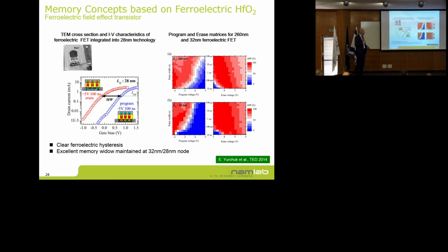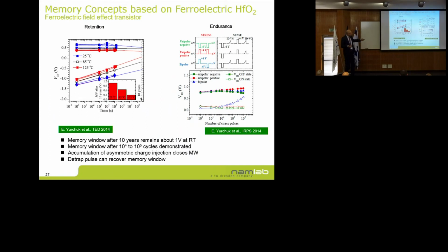And this slide shows that it really scales very nicely. So it compares ferroelectric field effect transistors that we fabricated together with Global Foundries with 260 nanometer channel length and 32 nanometer channel length. And you see that the programming curves are more or less identical. And also retention is good. And cycling is more limited than in the capacitor case, because charge trapping is happening, as I showed you from the model. And in the transistor case, you are sensitive to the charge trapping. The transistor will react. So the window will close after about 10 to the 5, 10 to the 6 cycles. Currently, we think we can drastically improve it, but this is the actual status.